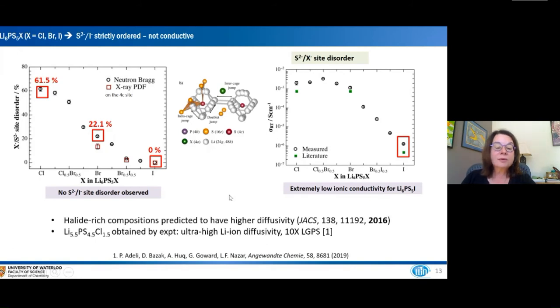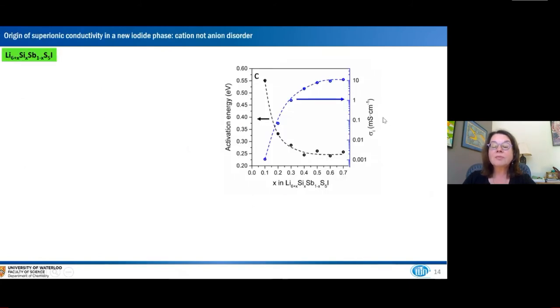Now it turns out that halide-rich compositions have higher diffusivity. This is reported in a paper in JACS. We've been looking at halide-rich compositions reported here in this paper of Angewandte Chemie, and we're able to get ultra-high lithium-ion diffusivity, 10 times that of the lithium-germanium phosphosulfide, but I won't have time to talk about that. I'll just mention our work on the Argyrodite iodides, where we effectively, by introducing antimony into the lattice, substituting - these are antimony, silicon substituted antimony Argyrodites.